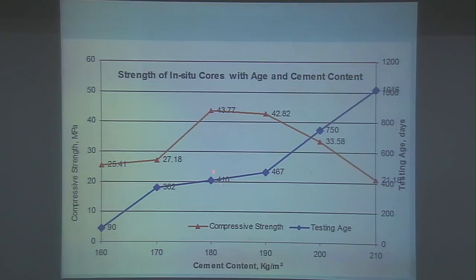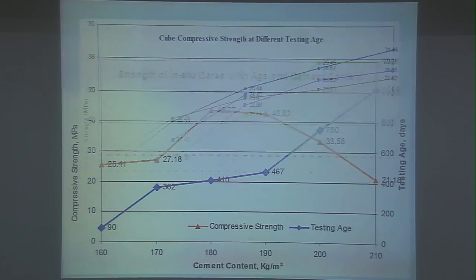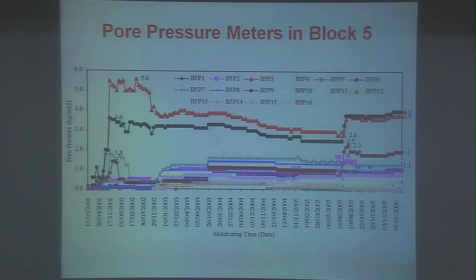strength of the concrete. After 410 days, it was 43. And after that, we were not getting even an increase in the strength. We were getting a reduction in the strength even by increasing time. So this is the kind of data we can get from this. This is the pore pressure meter.